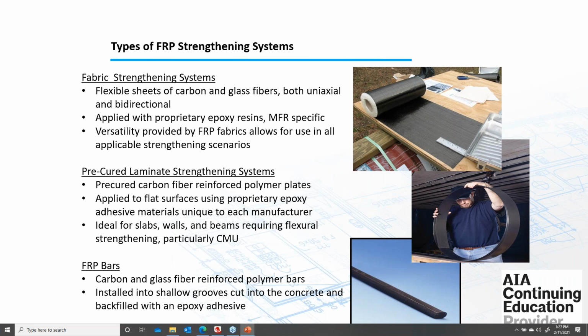Then there's the FRP bars. These are carbon or glass typically. We'll apply these by cutting a shallow groove into the concrete, in what we call a near surface mounted application. Imagine you have, say, a parking garage and you've got a negative moment issue right in the drive lane. Well, we can't put a plate or a strip of fabric on the top of the concrete where cars are going to be driving over it. Obviously, that's going to damage the system. So with the bar, you can cut a small groove into the concrete and kind of internally reinforce the concrete, so you're protecting the FRP from pedestrian or vehicular traffic.